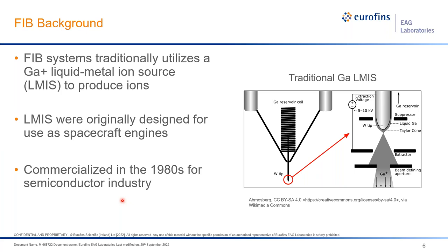In the LMIS, there is a sharp tungsten needle attached to a resistive metal basket coil, a reservoir that's filled with gallium. This basket is then heated and liquid gallium flows down to the tip. Here's a zoom in of that tip there. And then we use a high voltage to shape the end of the wetted tip into what's known as the Taylor cone, and extract gallium ions, which are then focused with a variety of electrostatic lenses and accelerated towards the specimen.